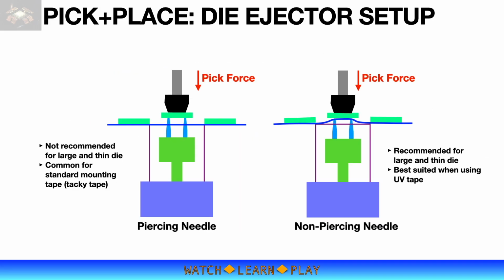Another thing to consider is the needle tip radius. A piercing needle has a small tip radius. It pierces through the tape and may cause microcrack on die backside during pickup, as the pickup tool is pressing on the die and against the needle. This is especially true for large thin die.